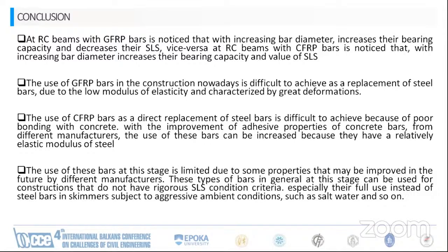The use of CFRP bars as a direct replacement of steel bars is difficult to achieve because of the poor bonding with concrete. With the improvement of adhesive properties of bars from different manufacturers, the use of these bars can be increased because they have a modulus of elasticity relatively close to steel. The use of these bars at this stage is limited due to some properties that may be improved in the future by different manufacturers.